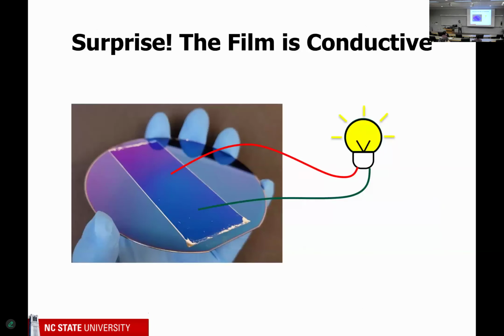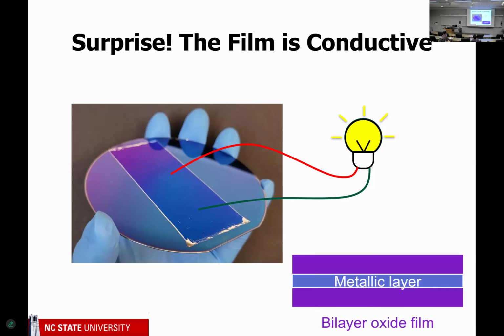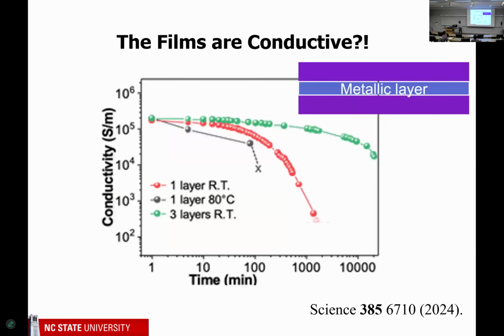Now, the really surprising thing, I thought, okay, depositing oxides was cool, but if it's just an amorphous oxide, it's only got limited applications. But it turns out this film is quite conductive. That's weird. It's very, very weird. And so we think, I'm not going to show you all the evidence for it, but we basically think that there's a metallic-like layer in the middle. So remember where I said, remember it's gray? That's evidence that there's some metallic character to it. So if you measure the conductivity, I don't know if these numbers mean anything to you, but most metals are around here, 10 to the 6. So it's almost got metal-like conductivity.